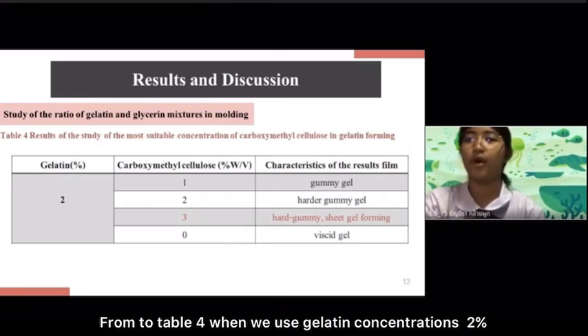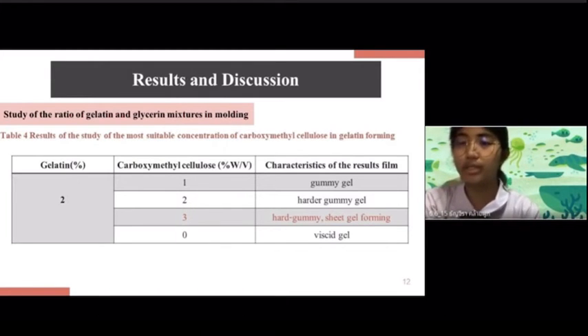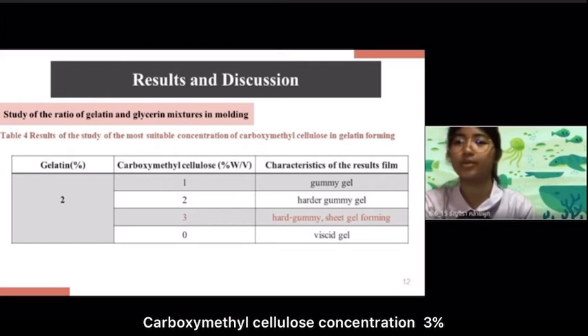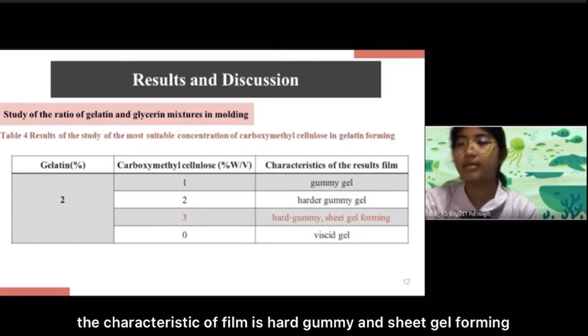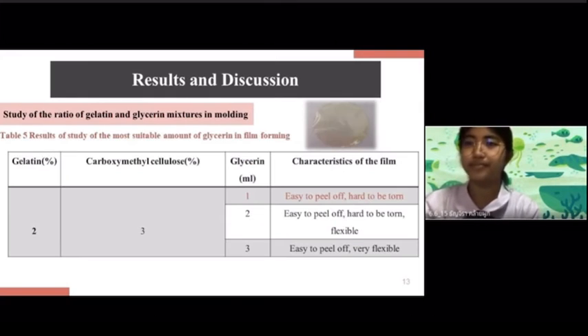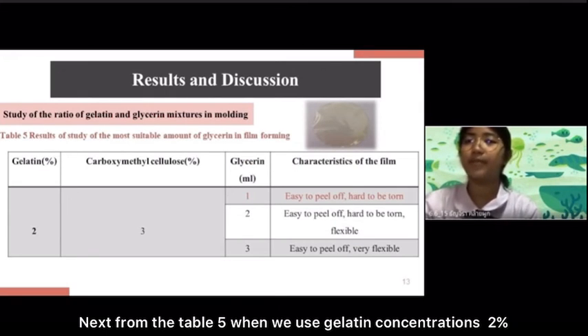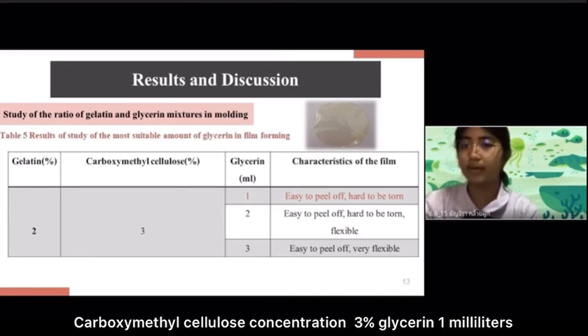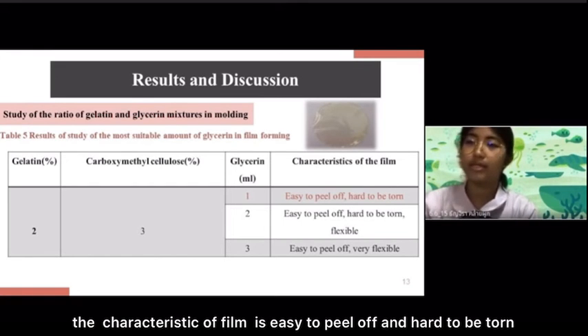From Table 4, when we use gelatin at 2% concentration and carboxymethylcellulose at 3% concentration, the characteristic of the film is hard, gummy and sheet gel forming. Next, from Table 5, when we use gelatin at 2%, carboxymethylcellulose at 3% and glycerin 1 milliliter, the characteristic of the film is easy to peel off and hard to tear.